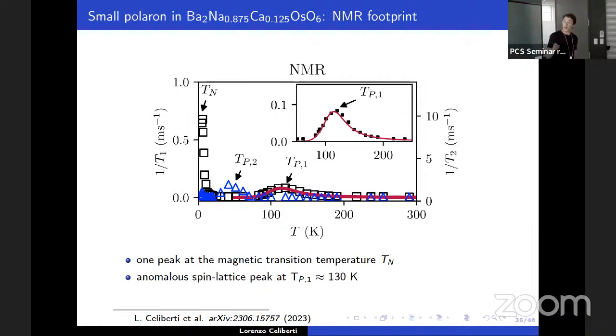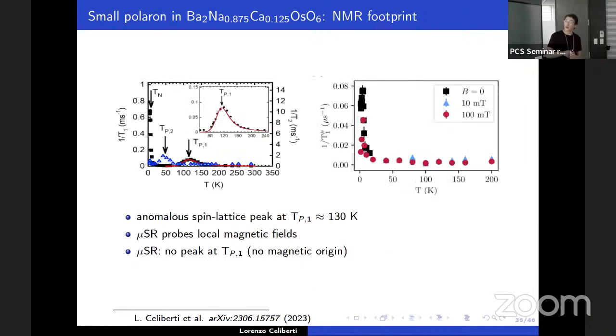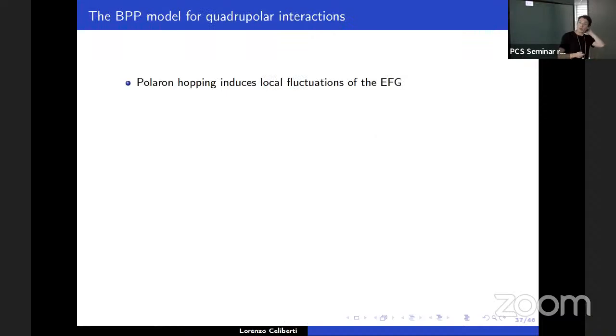And also, muon spin rotation measurements have been performed, and they didn't show any corresponding peak. And now with muSR, you probe the local magnetic environment. So this made us think that this is related to some charge hopping process. And so what can be done is to